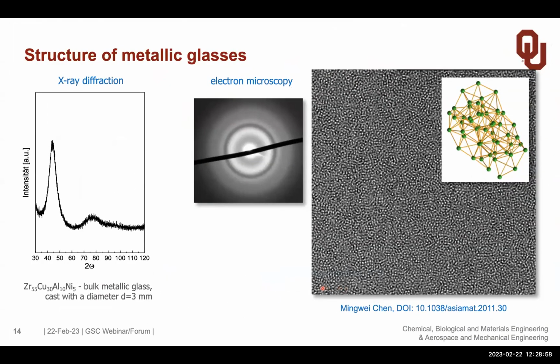Of course, it's a metallic glass. So if you do X-ray diffraction, you don't see sharp peaks anymore, but you see very broad peaks, and only 2 of them. You go to the electron microscope, you see something similar. If you go to high resolution electron microscopy, where you can see atomic columns in a crystalline material, here you see a disordered structure and some kind of a theoretical representation of that structure in the insert.